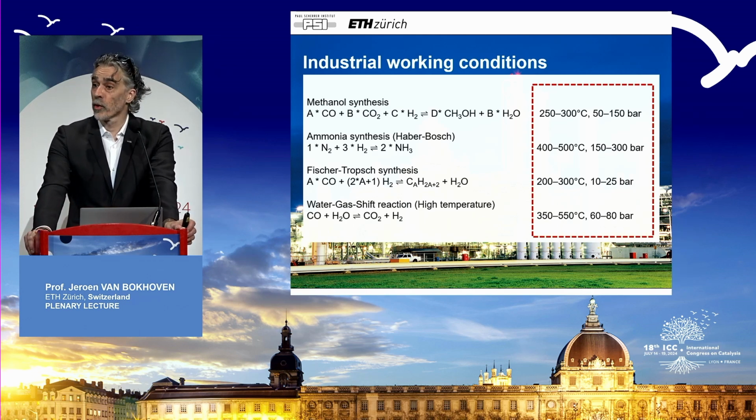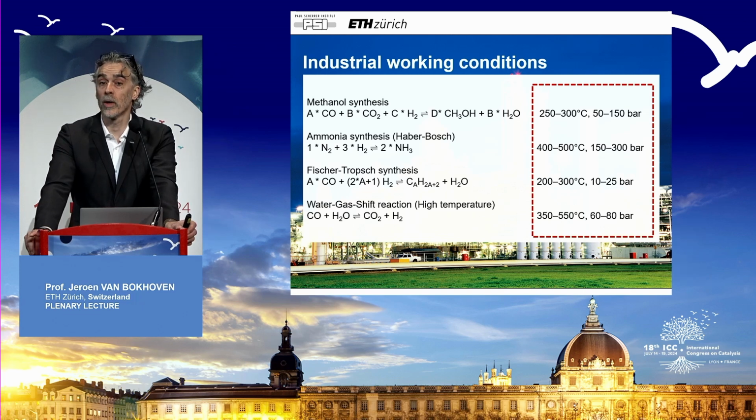If you look at industrial processes, for example methanol synthesis, which I will talk about today, they are at elevated temperatures and very often at high pressure. Ammonia synthesis, Haber-Bosch, very well known, is a high pressure process. Fischer-Tropsch is at elevated pressure. Water gas shift is done at elevated pressure and temperature as well. So if you want to understand the catalytic process, it's essential to look under the conditions where the catalyst is actually doing its function.